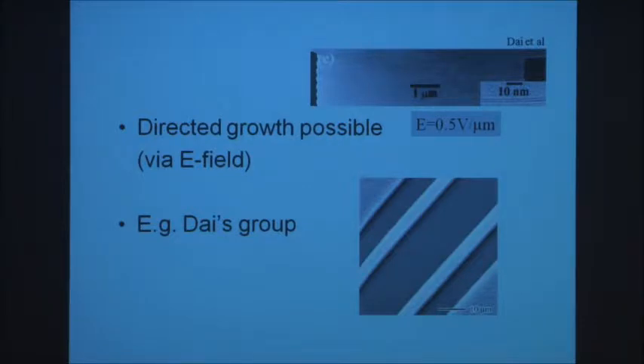And that's the big problem, because when you try and do something like that, what you tend to get is this. When you put two contacts down, you tend to get lots and lots of single wall nanotubes growing between the contacts, not just one of them. And if you've got more than two nanotubes, then the chances are one of them is going to be a metal. And if it's a metal type, then the off current is going to be, by definition, pretty high.